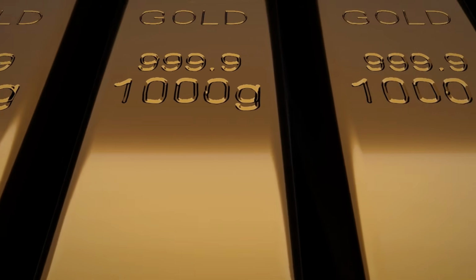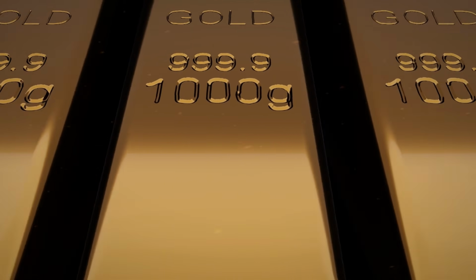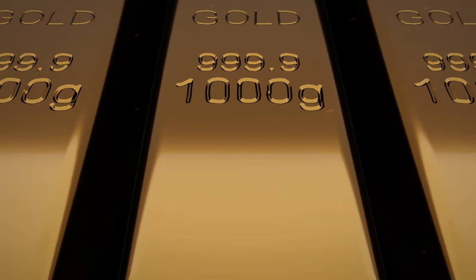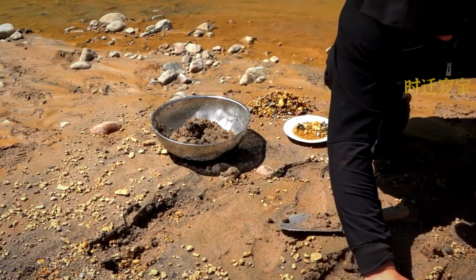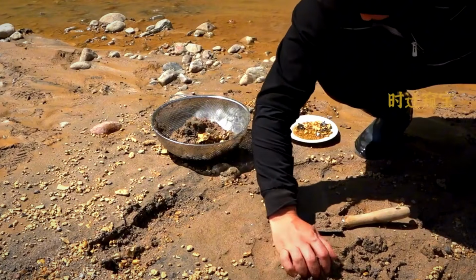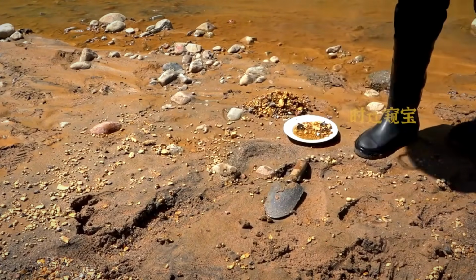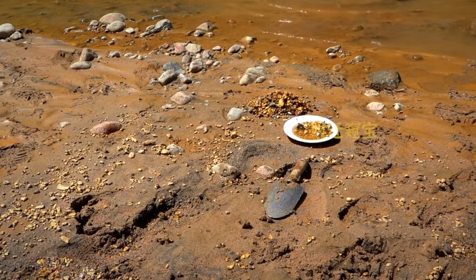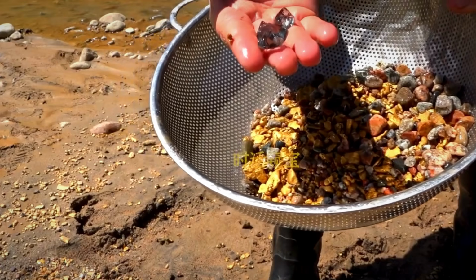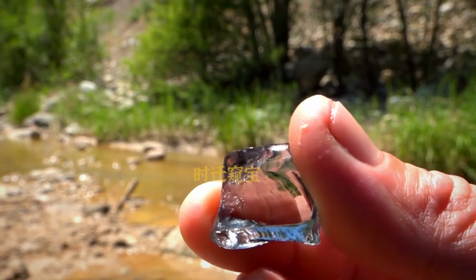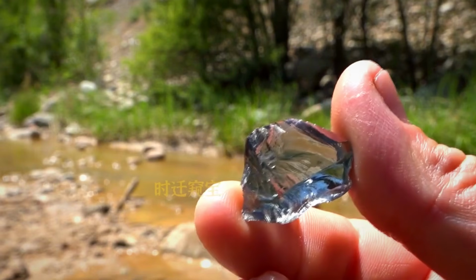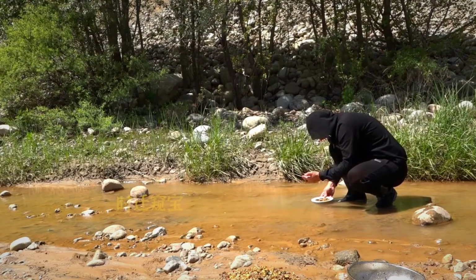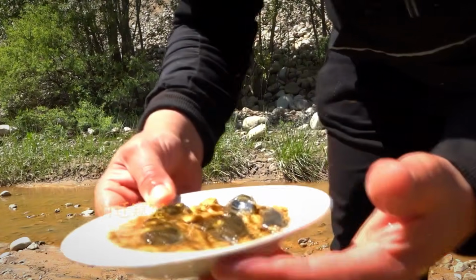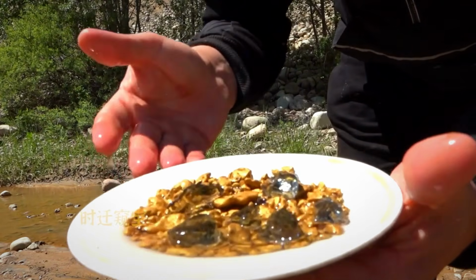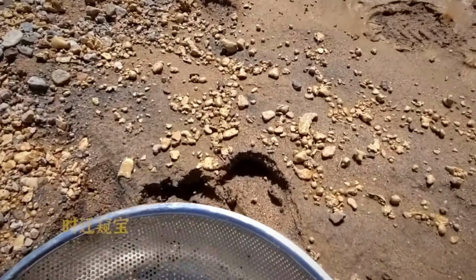To evaluate tailings, begin with a pan sample. Even if no free gold appears, a persistent black or brassy residue, particularly one that includes non-magnetic metallic particles, can signal refractory material. If the pan result is promising, assay selected samples from different sections of the pile, noting variations in grain size and oxidation level. In some historic camps, tailings from the final years of operation carry higher grades than the ore that initially justified the mine.